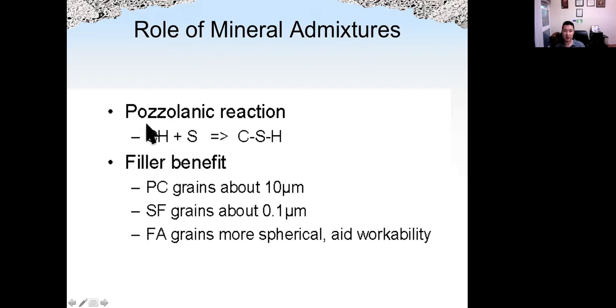For mineral admixtures, such as fly ash and slag, we know the pozzolanic reaction transforms calcium hydroxide into CSH. That is due to, first, the so-called filler effect. Because the Portland cement size is around 10 micrometers, and silica fume is around 100 times smaller, silica fume can fill the gaps between cement particles. Fly ash has a more spherical shape, which can increase the workability of concrete. Slag has a more angular shape, and its size is also similar to cement particles.